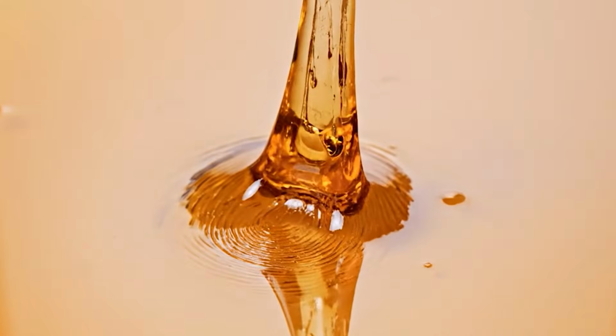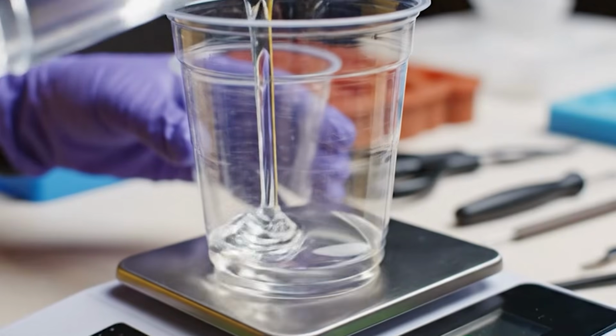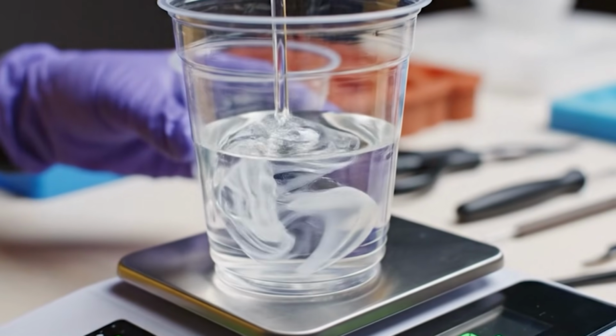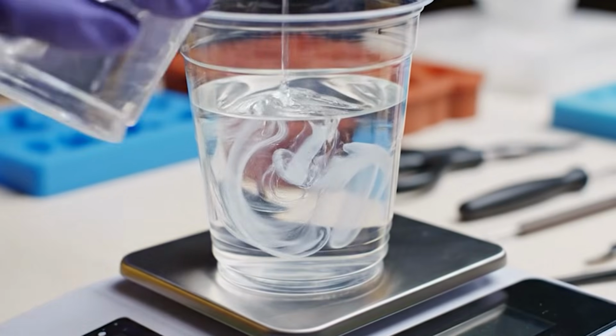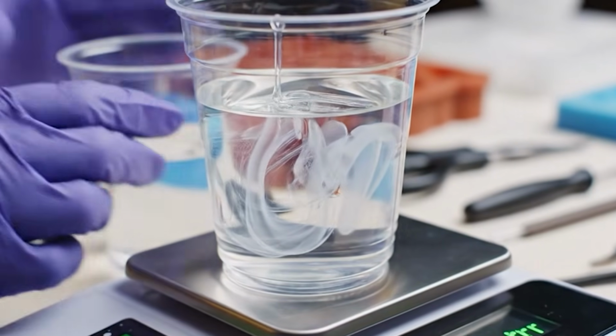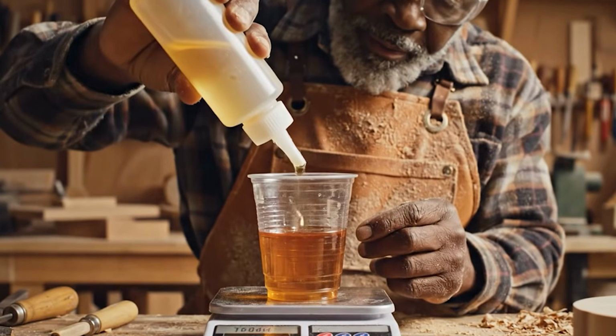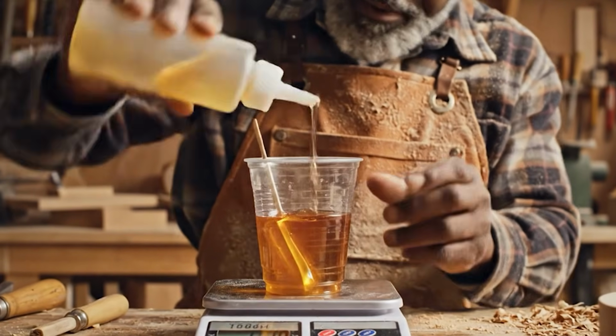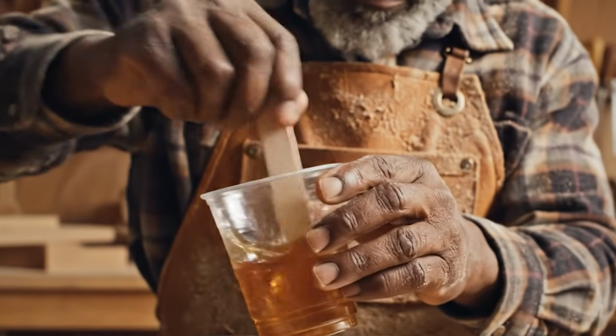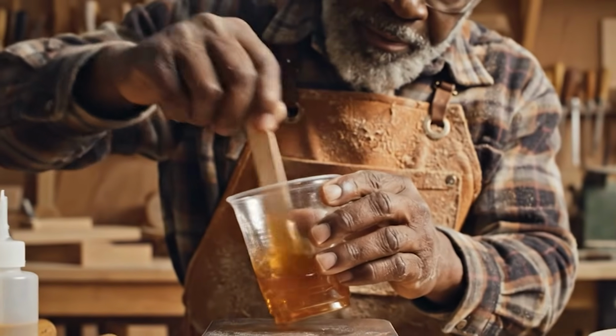This is almost always a mixing problem. You either got the ratio wrong or didn't stir thoroughly enough. There's really no good fix for this after the fact. You'd need to dig out the uncured resin and re-pour that section. The lesson here is measure carefully and stir longer than you think you need to.